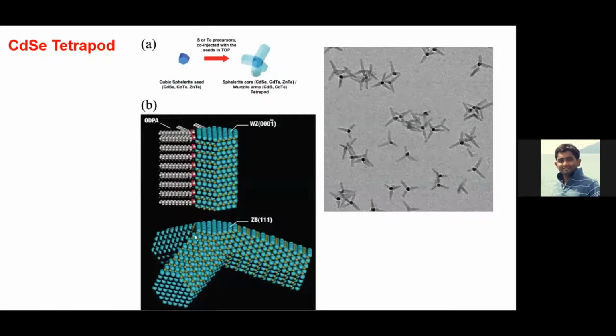A tetrapod means you have a head and four legs: 1, 2, 3, 4. Inside, the head part has a different crystal structure. It starts from the cubic structure, like cadmium selenide, cadmium telluride, zinc telluride, whatever you need. Here you can see the TEM images: the small dot is the head, and it has four legs. You can see three legs in TEM because it's a two-dimensional image but your particle is three-dimensional, so one leg you cannot see because it's above the head.